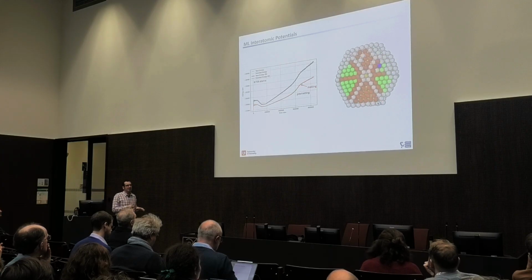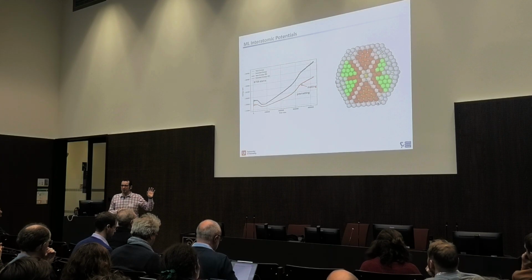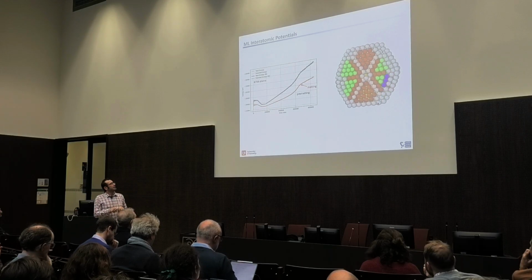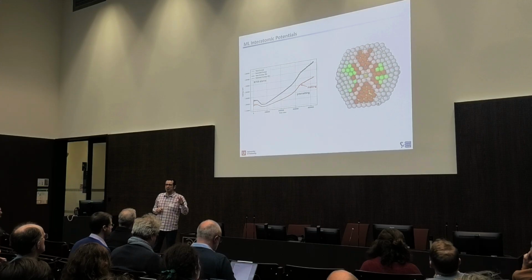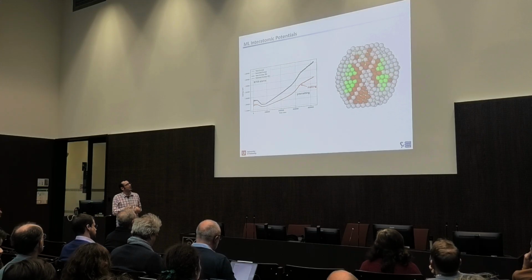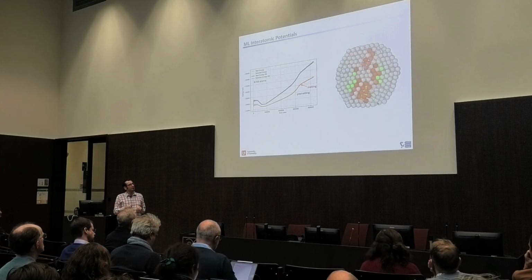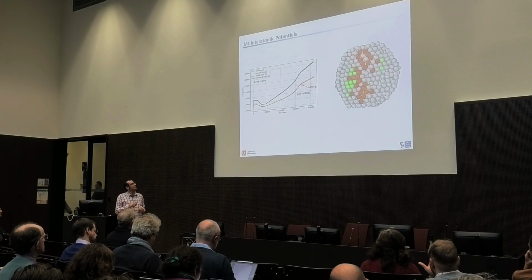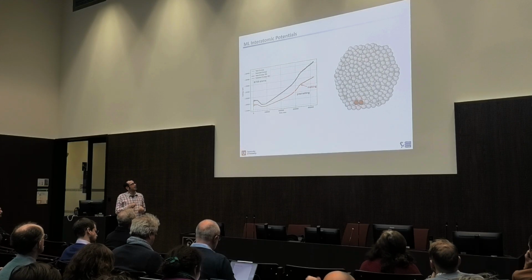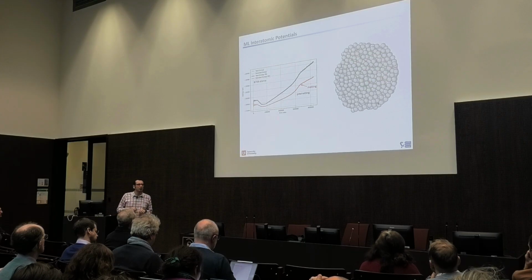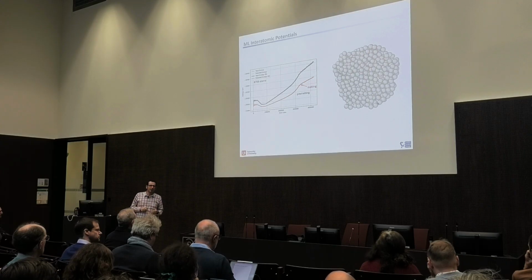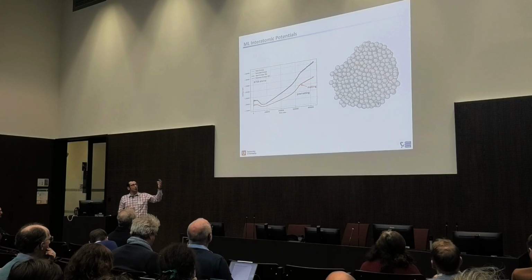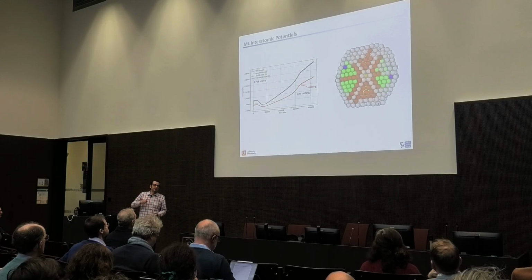Okay, then as I said, currently we still work on this problem. We can generate accurate potentials in order to understand the dynamics of materials. This is the application for melting. For example, we start simulating a large particle, we increase temperature little by little, and we see here a melting point. Therefore, we can understand the melting nature of these large nanoparticles with different shapes.